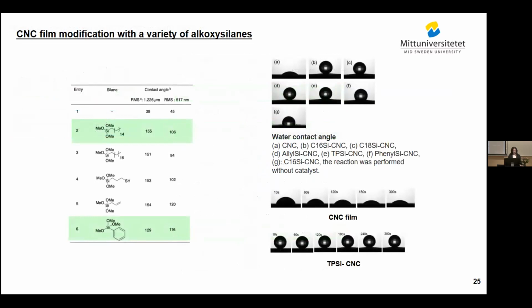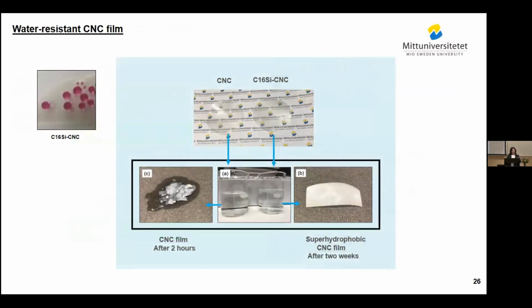I did the same reaction, but with a variety of alkoxysilanes. But this phenylsilane shows us that not only the roughness of the surface is important, also the chemistry of the surface is important, because with this chemical, I couldn't reach a superhydrophobic surface even at high roughness. I don't want to spend time here. These are the contact angles.